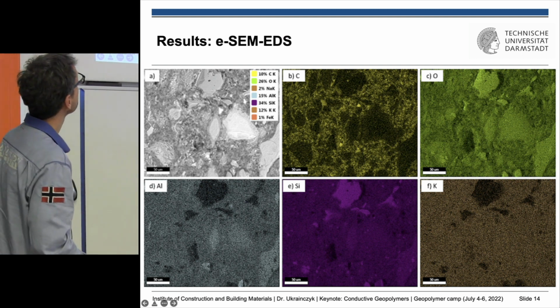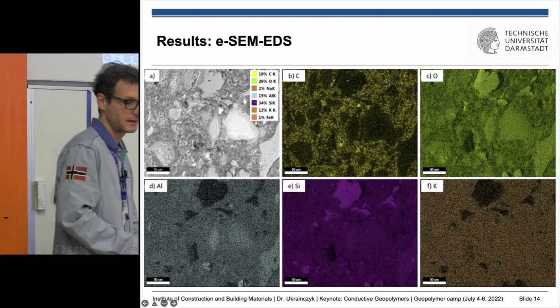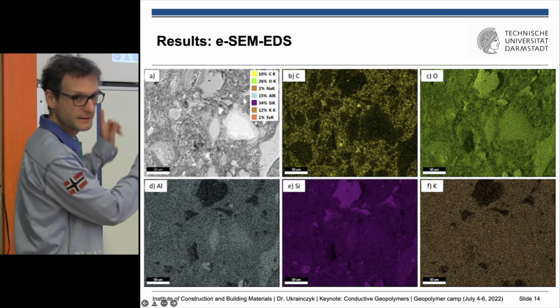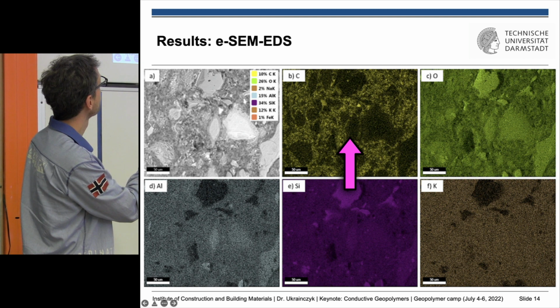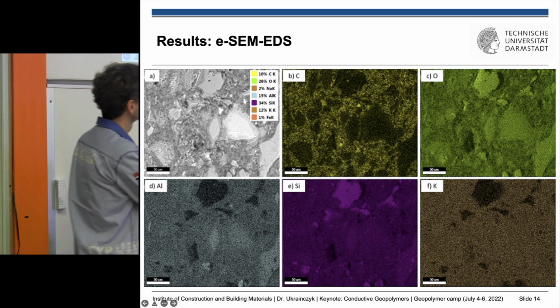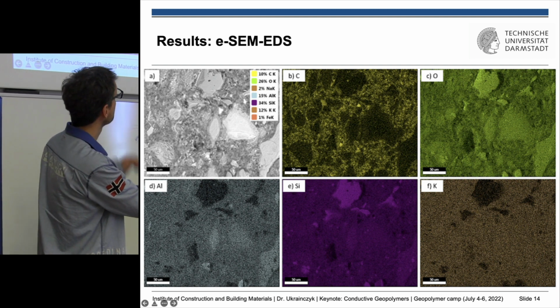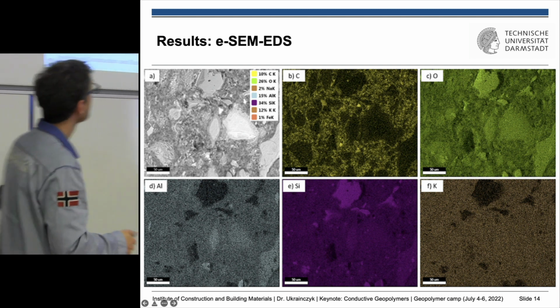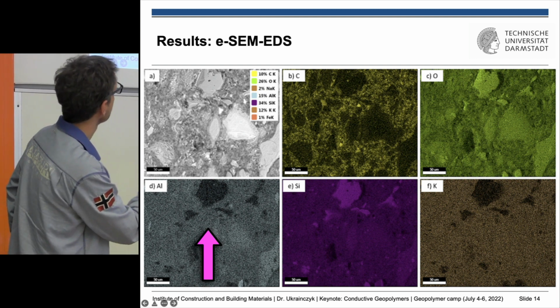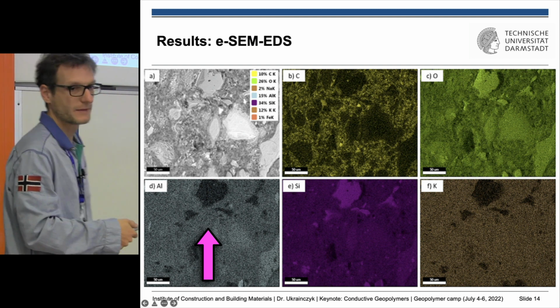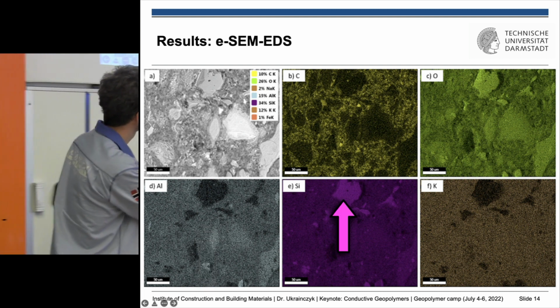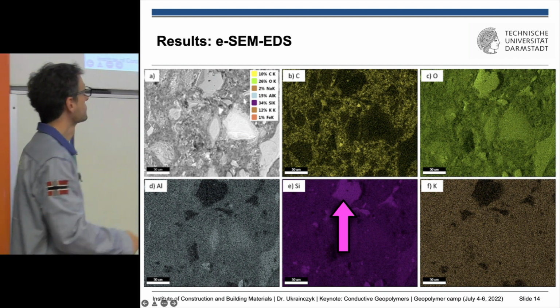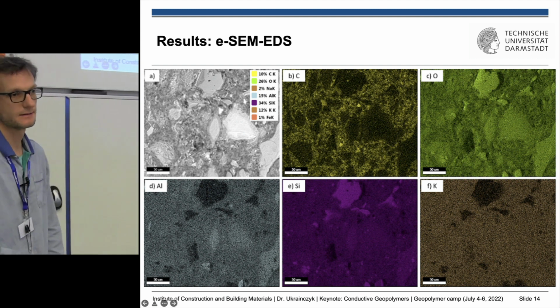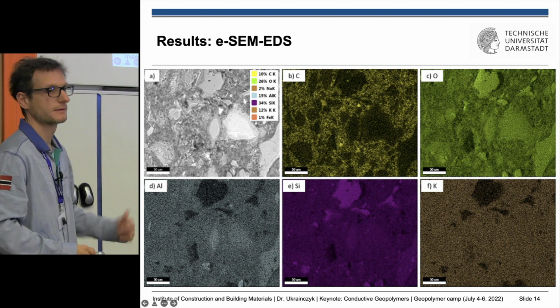chemical analysis by microscopy, so EDS mapping, and you can see those black by backscatter. This is the backscatter image, so the black is the carbon, and we also identified it by carbon. You can see that it's this yellowish color, and it's very well dispersed. And by silicon and aluminum, we can see the metakaolin particles, but also there is a quartz. For example, this is a quartz particle. So this is because we are using that ferro-sialate metakaolin, the red clay.